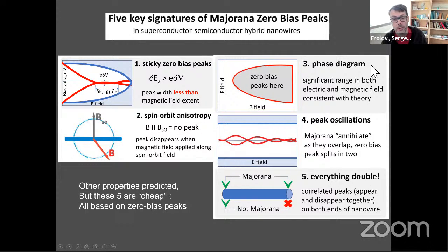Now, the third one is we have these theories from 2010 and then several hundred papers after that have mapped out the parameter space in gate, magnetic field, and other parameters where Majorana should appear. So it is not just tune the knobs and see a peak, oh, it's Majorana. It is actually a regime in parameters that can be understood, analyzed, and checked back to a model to see if it makes sense. So the idea is map out where the effect appears and compare it, fold it back onto some basic model. We have also done that on at least one occasion, to find a region of parameters where the zero bias peak appears compared to a simple model.